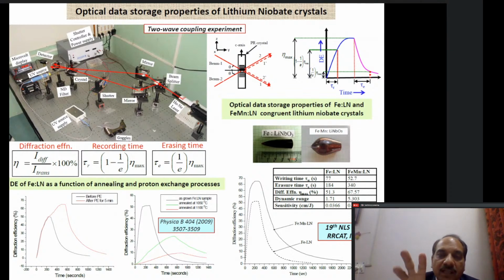So once this refractive index profile has been formed, it behaves like a Bragg grating, and it starts to diffract the same beams which have formed this refractive index profile inside the crystal. And this process of formation of the refractive index grating, diffraction from that grating, and then erasure of that grating is what we record.